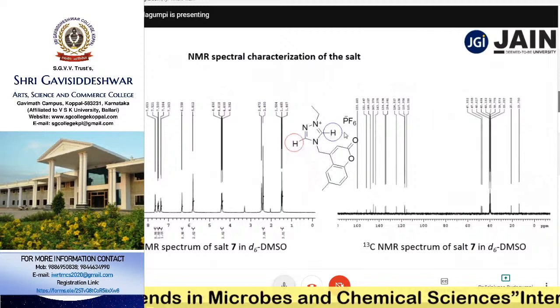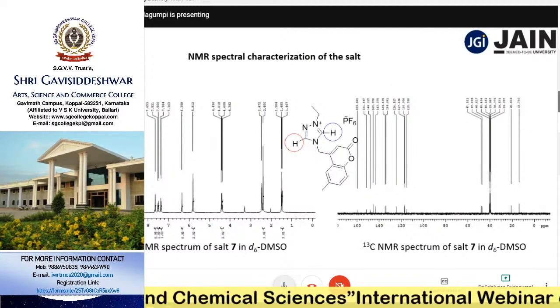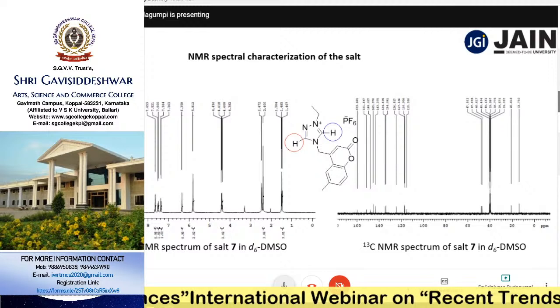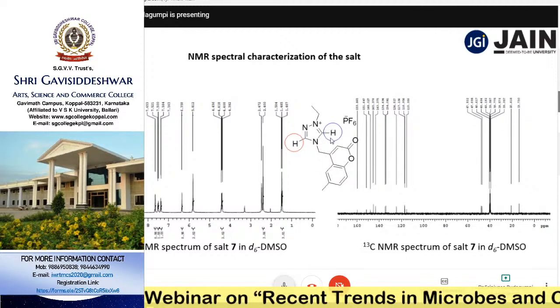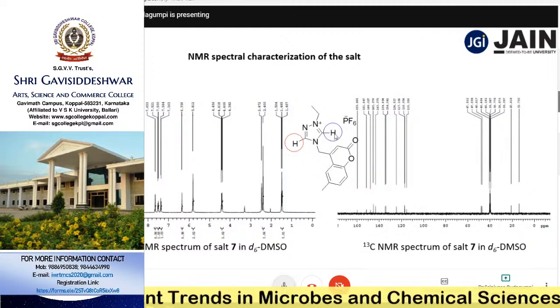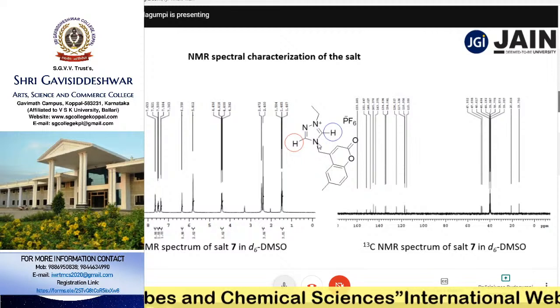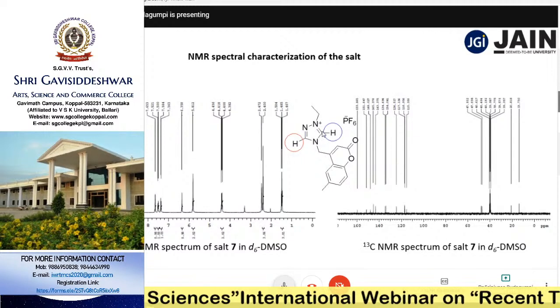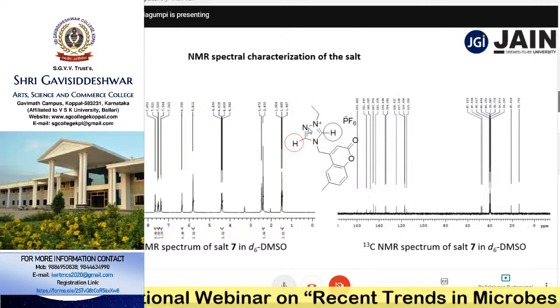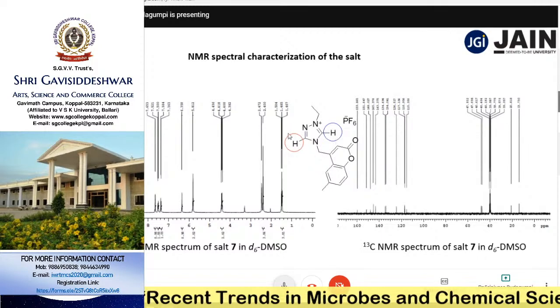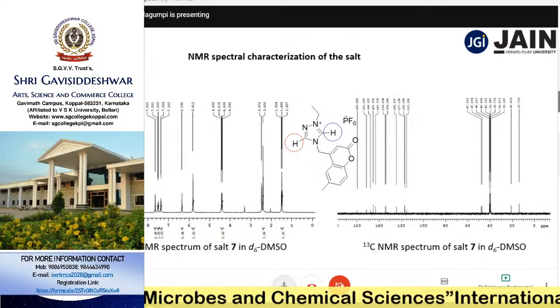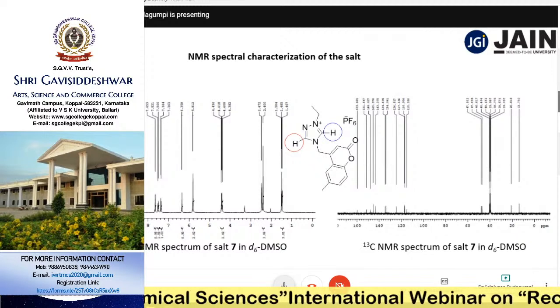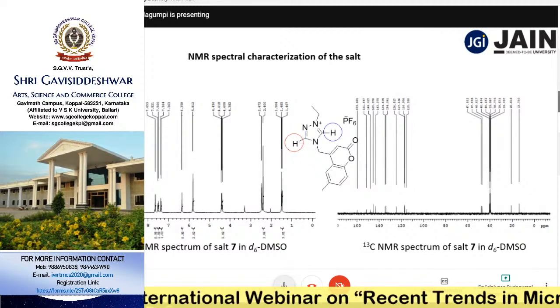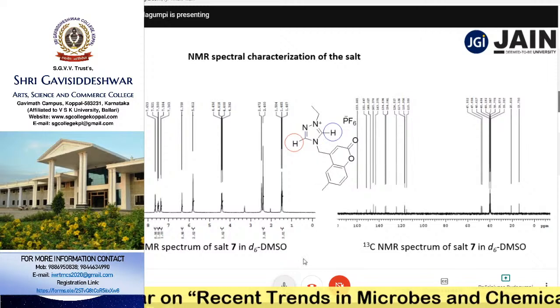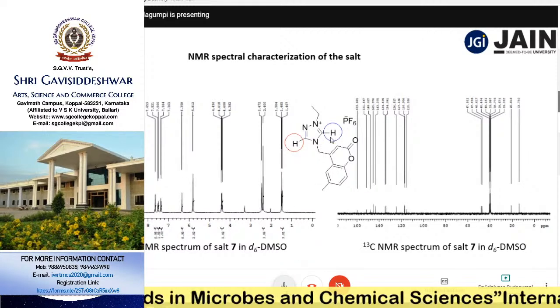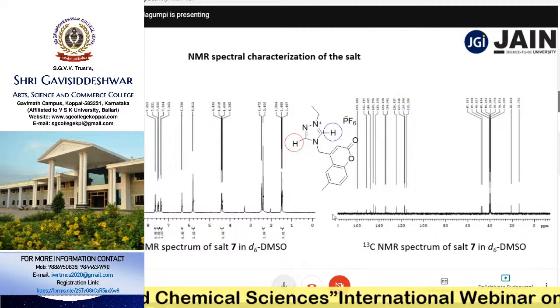and these were resonated at 9.2 and 10.17 delta ppm respectively, right? This is because this particular proton is highly deshielded due to the presence of two substituted nitrogens attached to the carbon atom, while here this nitrogen is substituted but not the other nitrogen. Because of that difference in the deshielding, the C5 proton appears at 10 and the C3 proton appears at 9 usually, and this matches well with the literature data as well. The rest of the proton resonances are in accordance with what we expected.